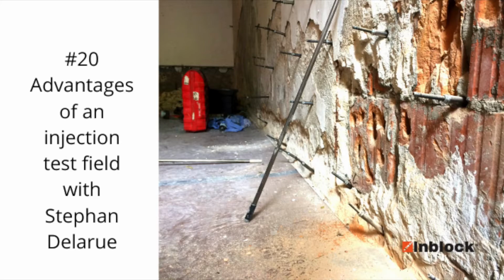But on the other hand, I also did a test injection, also in a tunnel, but the target there was not a curtain injection behind an unknown structure. It was inside the concrete structure. So they had different spots there in that tunnel, but they had no clue about the concrete strength. It was an old concrete, I think 25 years old, or older. And the target there was to strengthen the structure finally.